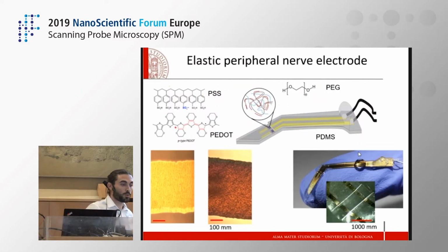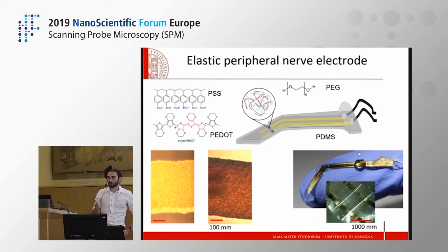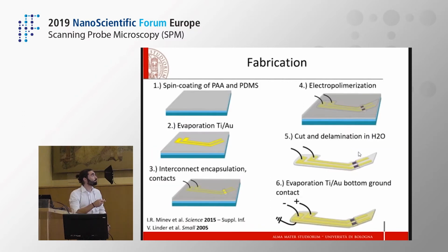Here is the device configuration. It is based on two metallic stripes that are encapsulated in two PDMS layers, leaving an open trench 400 micrometers wide for the coating of the electrodes, which are coated with PEDOT:PSS PEG. We introduced the PEG as a plasticizer in order to improve the elasticity of our electrodes, and here you can see the uncoated and the coated electrode optical images together with a picture of our electrode, which is basically the dimension of the tip of a finger.